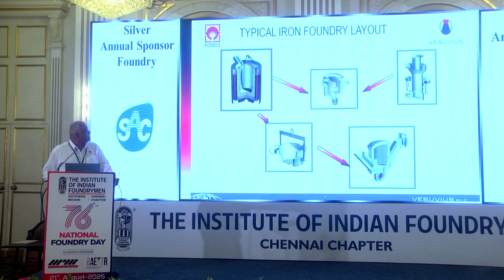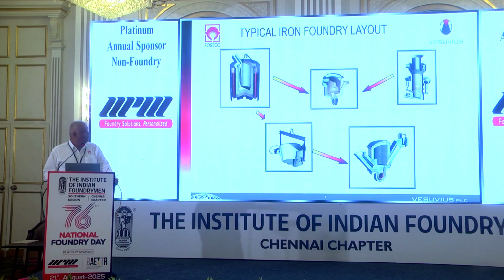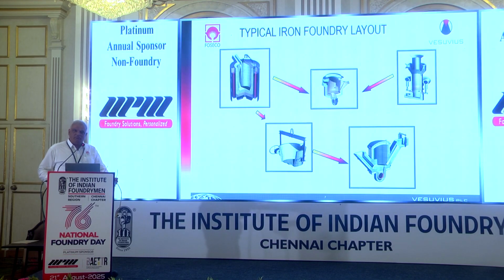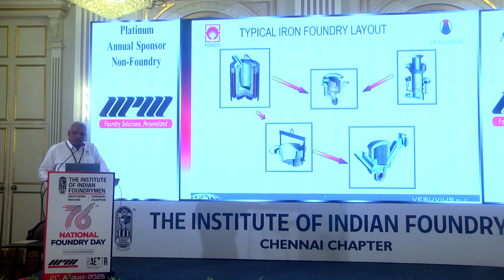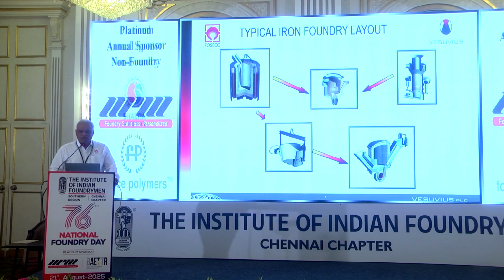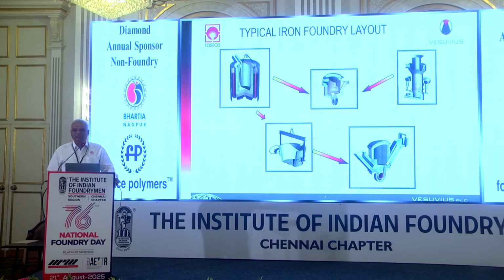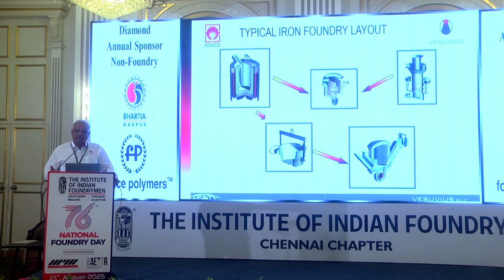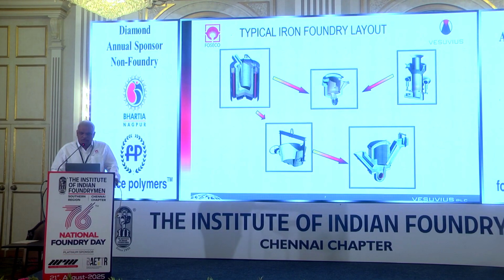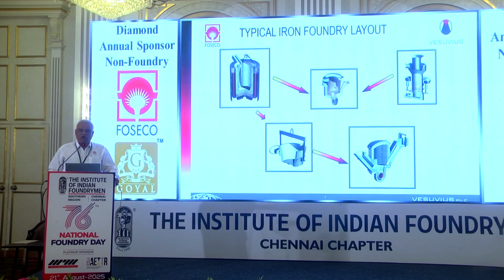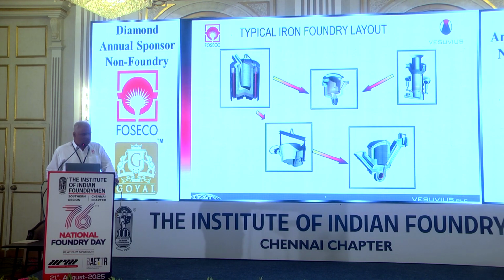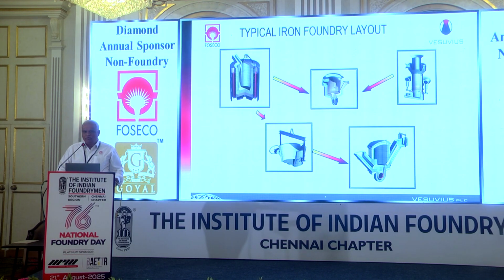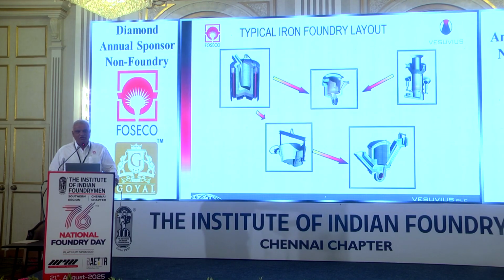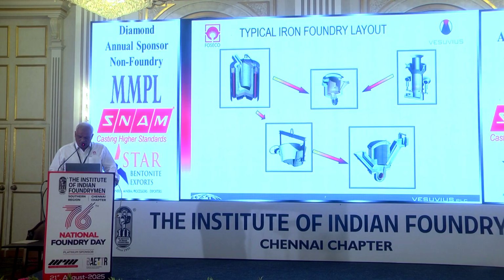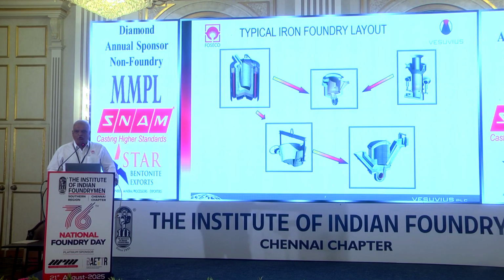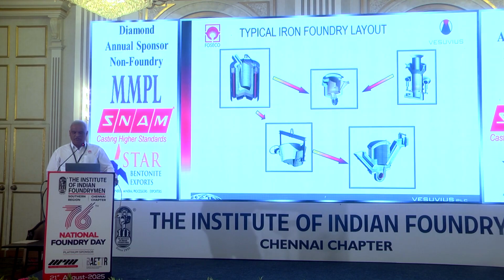Similarly, you can see the layout for the iron foundry. In an iron foundry, the metal is melted in a cupola or induction furnaces. Nowadays high pressure molding lines are increasing, and in most cases they are on a high pressure line. Everybody is using an auto pour system, maybe press pour or Tundish auto pour system. In that case, material is tapped from the furnace to the ladle, then from the ladle to the press pour or auto pour, and from that it is poured into the mold.